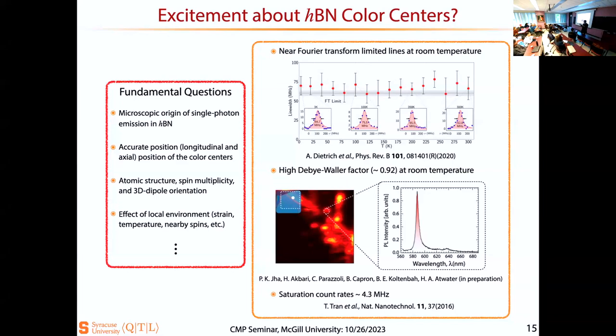So by reducing the temperature, we were able to get rid of phonons. But then we also apply the electric field to get rid of the charges that are there and get the line width, not emission, but absorption line width, close to the Fourier limit. So it's always spectral diffusion and interaction with phonons.